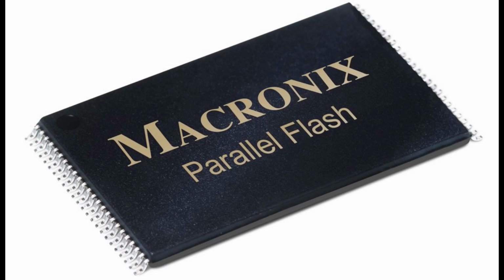Such high voltage densities can break atomic bonds over time in the relatively thin oxide, gradually degrading its electrically insulating properties and allowing electrons to be trapped in and pass through freely, leak, from the floating gate into the oxide, increasing the likelihood of data loss since the electrons, the quantity of which is used to represent different charge levels, each assigned to a different combination of bits in MLC flash, are normally in the floating gate. This is why data retention goes down and the risk of data loss increases with increasing degradation.